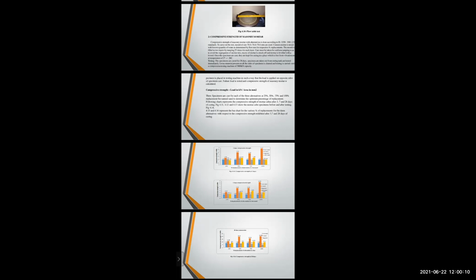Lead shot is used to balance the lever arm, which is placed inside a measuring jar. The briquette specimen is firmly placed, lead shot is released from the top, and the amount of lead shot collected in the measuring jar is weighed. Tensile strength is calculated by the formula P into LA divided by area.